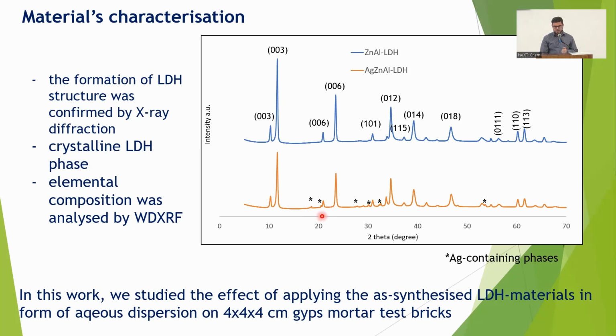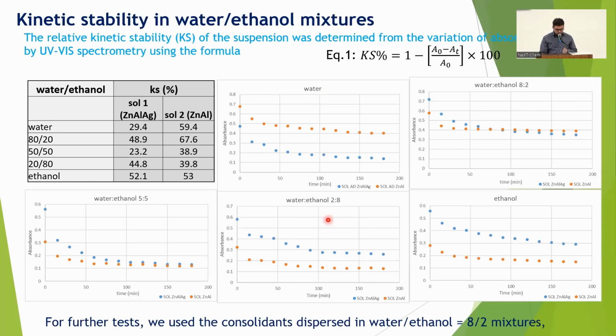In order to study the effect of these consolidants, we decided to study their kinetic stability in various solvents: water, ethanol, and water-ethanol mixtures. Depending on the nature of the solvent, their kinetic stability varies a lot. We observed that the addition of silver in the synthesis has changed the properties of this material. Indeed, we found that among the mixtures used, the water to ethanol 4:1 mixture is the most stable dispersion. So we decided to disperse the consolidants in this mixture in order to test their properties as consolidants.